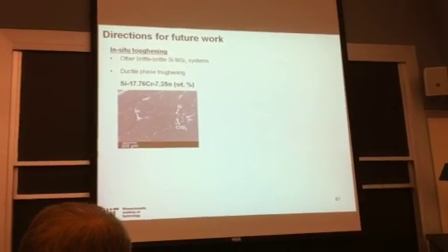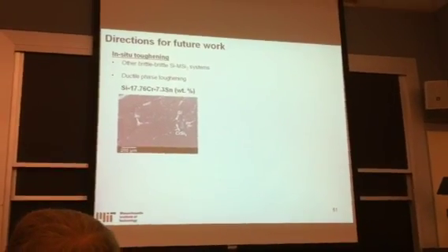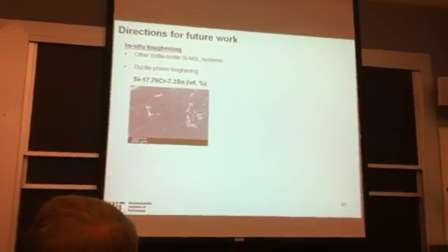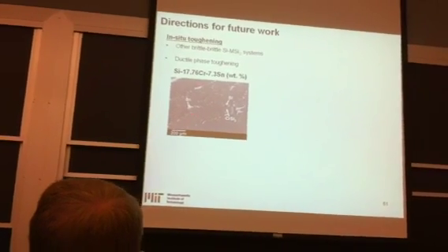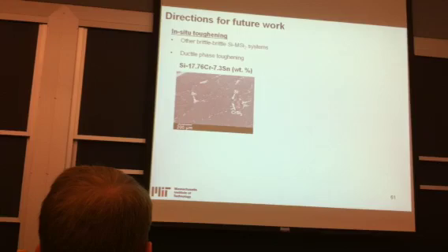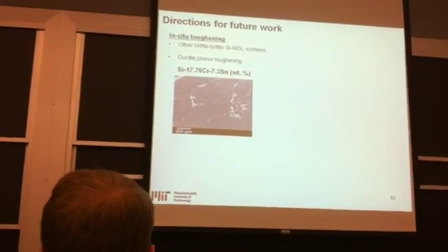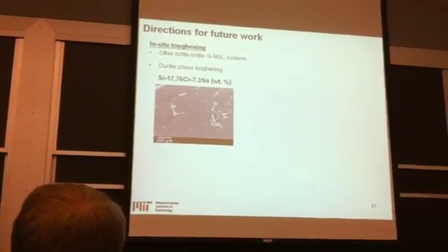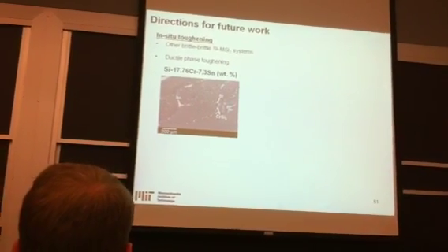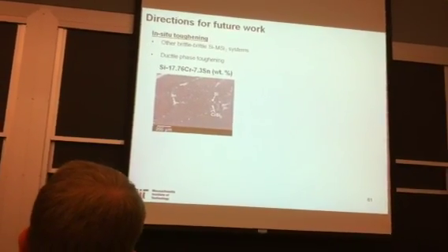Chromium, during solidification of these alloys, we see that the tin actually segregates to those eutectic colonies that you saw in the silicon chrome disilicide alloys. So what we would expect is we would achieve the same type of toughening within these eutectic colonies, but we'd actually achieve other toughening mechanisms at the colony boundaries, such as crack blunting or crack arrest, which is actually shown by this Vickers indentation on this alloy on the right-hand side.